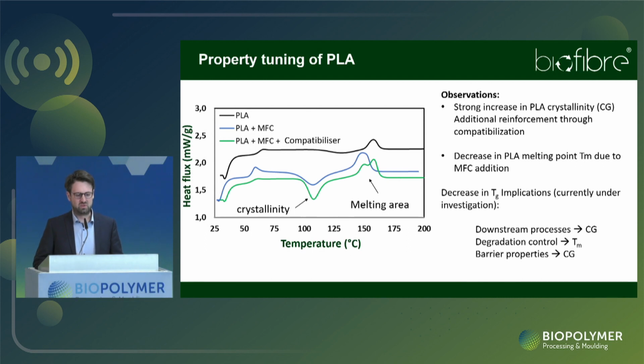And to our astonishment, we could reduce the melting area to lower values, which can help as well for various applications like different self-fiber reinforced applications where you talk about crystalline materials and amorphous materials, which can really be beneficial. We saw as well that you can have degradation control through the reduction of the melting point, which is more or less as well, empirically at least, related to the intermolecular forces between the chains, which means as well that the accessibility of those polymeric chains is better for microorganisms, and you have some barrier properties enhanced, in particular oxygen.